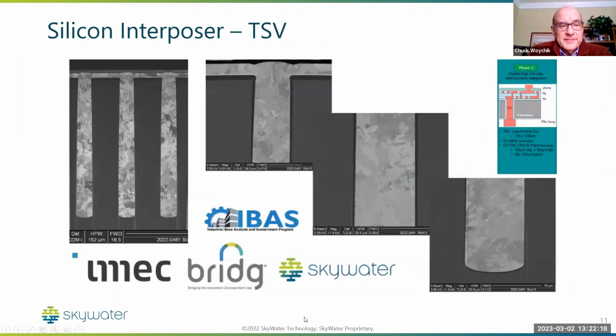Next slide, Alan. What this is showing is the core technology for a silicon interposer with a through silicon via, and this is showing the capability that we have now at SkyWater, which is a blind via, so it's a bottom-up fill chemistry. And the important thing to show here is that what we get is a TSV with no seams, no voids, and you have the nice equiaxed crystal structure. So this is an important capability that we now have to enable the TSV-based interposers. Next slide, please.